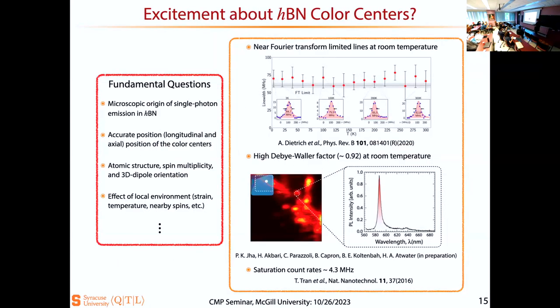So can you explain, this line width, is that just the homogeneous problem? At room temperature, no, it is not homogeneous. So what is causing the problem? There are two things, spectral diffusion and phonon line width broadening. One of the results I'm going to show you is at 6.5 Kelvin, and using Stark shift, we were able to narrow it down to within a factor of 2 of the line width limit.